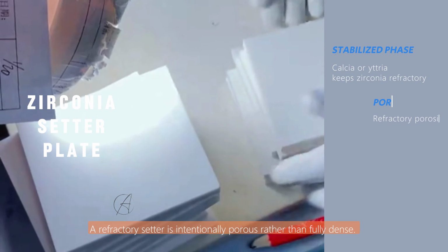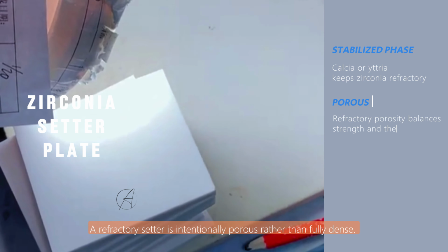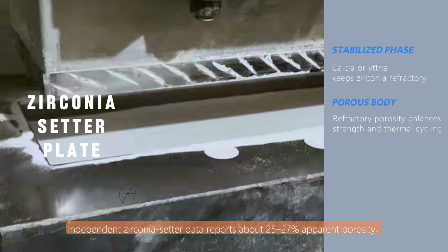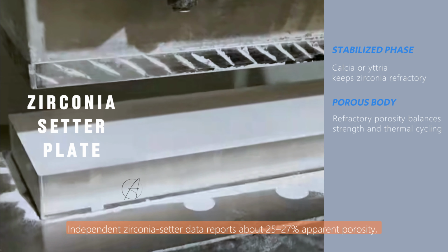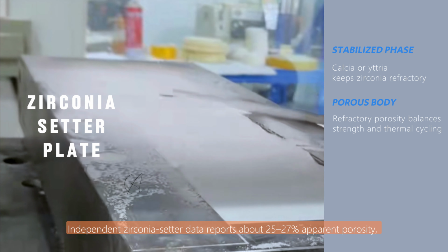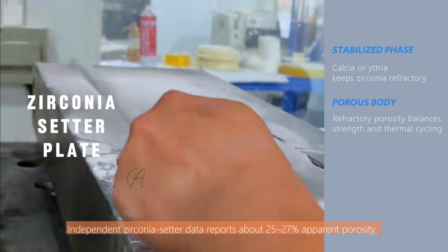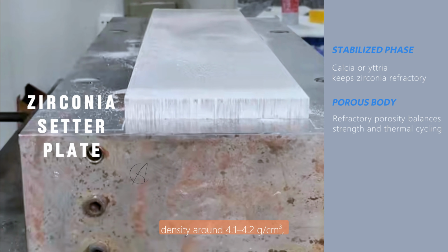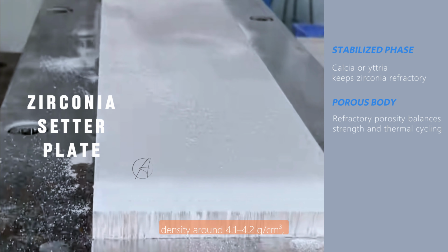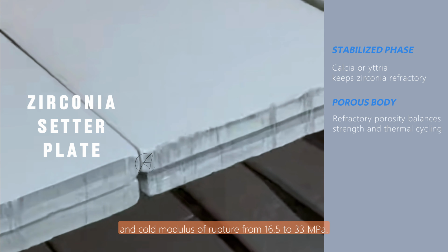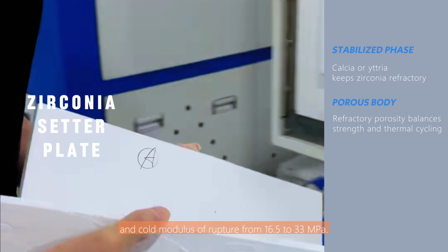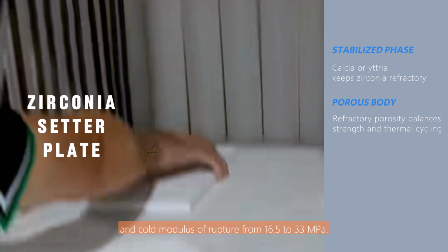A refractory setter is intentionally porous rather than fully dense. Independent zirconia setter data reports about 25 to 27% apparent porosity, density around 4.1 to 4.2 grams per cubic centimeter, and cold modulus of rupture from 16.5 to 33 megapascals.